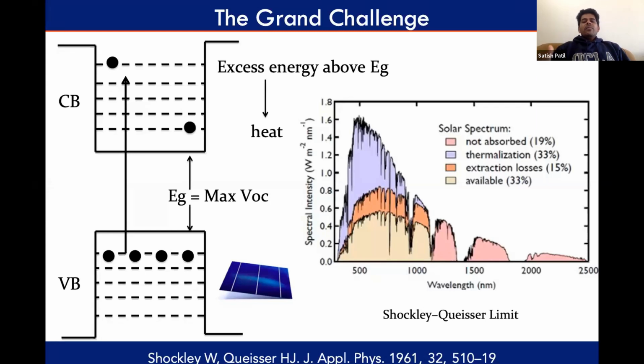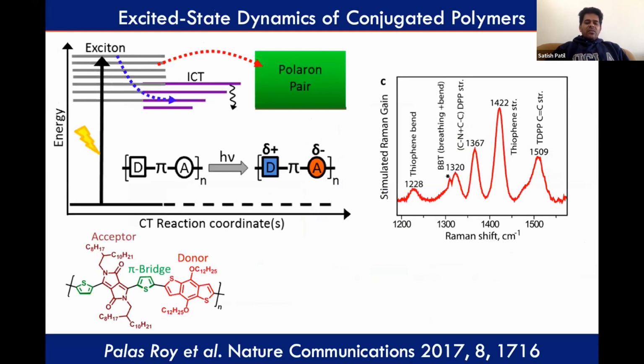But within that window of 33%, how are you going to maximize the efficiency? So this is the question we ask, and we first did a beautiful piece of work where we looked at how this bridge plays a role in the excited state. We did this by using a femtosecond Raman, because vibrations are the probes we use, and the excited state in an organic we call an exciton. You shine the light, you create this Frenkel exciton, and we understood the preferred route is this red line.